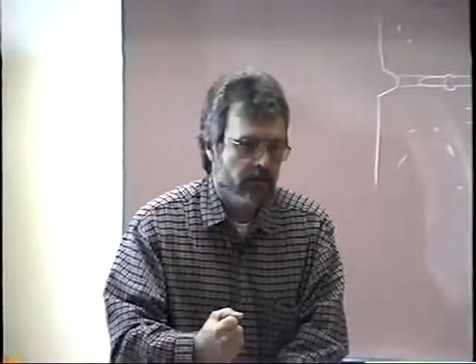Okay, as usual, a long arc is maintained until it has stabilized and the gaseous shield is formed. If you notice, when you first strike the arc, of course, it's a little unstable. So you want to allow it to long arc a little bit, and just a little bit, until the arc is stabilized. Then you move in close and back to where you want to pick up the bead from. Then it's shortened to a 32nd of an inch above the root face and held in place until the keyhole is formed. When this occurs, the weld is started using the whipping procedure.